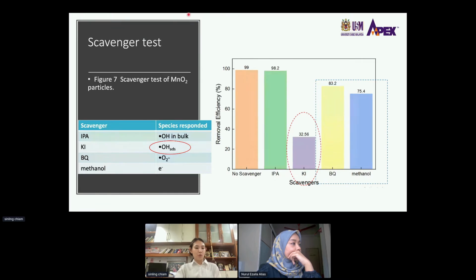Besides, scavenger tests were also carried out to determine the main reactive species involved in the degradation of the RhB dye by our MnO2. From the test, we can find out that hydroxyl radicals were the major reactive species, while superoxide radical and methanol is a minor reactive species.